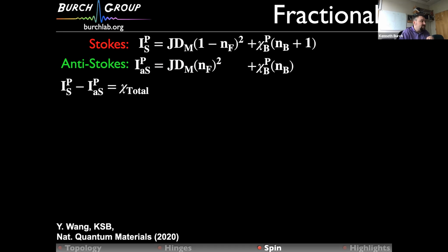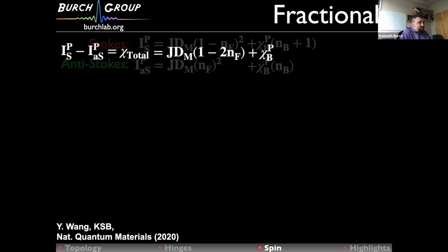So we realized that if we take the difference in the data, the Stokes minus the anti-Stokes, we would get the total susceptibility, which, in the case of the fermionic excitations, would cancel out this NF squared, and we would just be left with 1 minus 2NF. And it would cancel out the Bose factors, just by taking the difference. So we would really dramatically simplify our analysis.